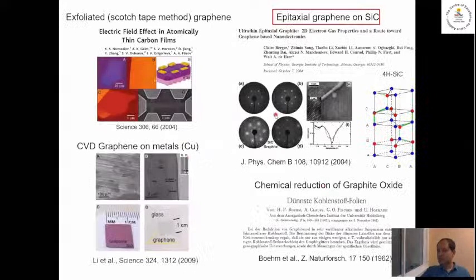So it turns out there are different forms of graphene. So this is graphene by Novoselov and Geim, right? This graphene is realized if you take graphite and put a piece of Scotch tape on it, you peel off the tape, and then there will be some graphene on your tape, right? So this is exfoliated graphene. And if you isolate that graphene and put contacts and so forth, you can do the things that Novoselov and Geim did. And these exfoliated pieces tend to be small, on the micrometer length scale.